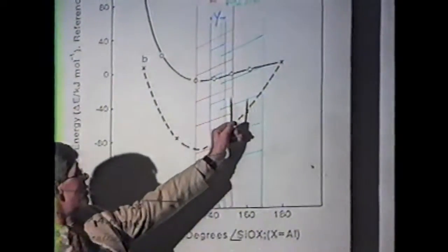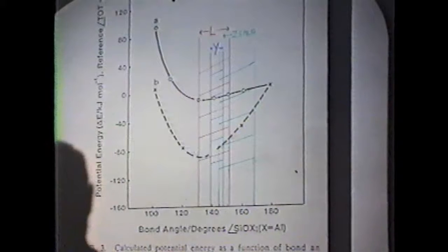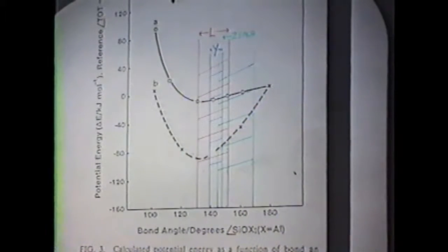And so the question is, where's the aluminum and which of those are the acid sites that are accessible? Which are the ones that I should put on this potential energy diagram to decide whether ZSM5 is acidic or not? In any case, the feeling that the order of acidity ought to more or less go in this direction would be consistent with the idea that has developed that the thing that might be unique about L zeolite as a support is the fact that it is basic.